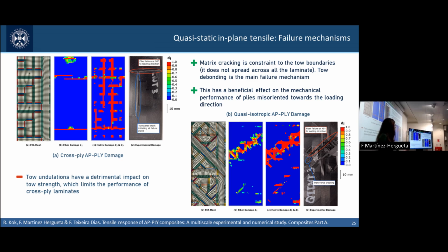That's something that we might have seen sometimes in wovens. Woven composites behave linear elastic until the onset of damage, despite having been cracked all over. If you go for some investigations on acoustic emissions, there's definitely quite a lot of matrix cracking, but you cannot appreciate it directly when analyzing the stress-strain response. This is more or less what we appreciate here. So that's already an initial advantage of these composites. Any questions up to this point?